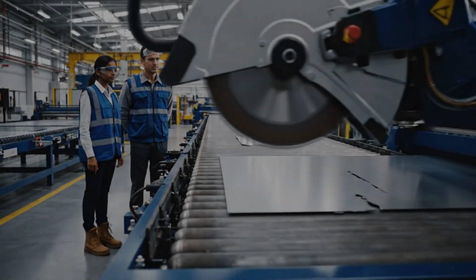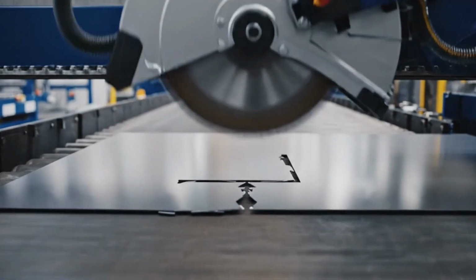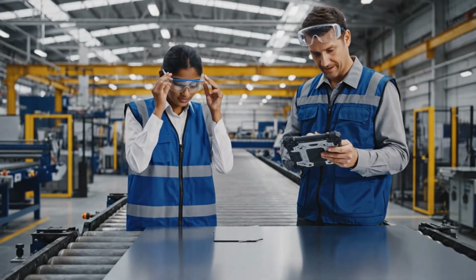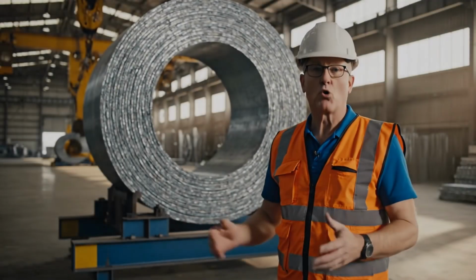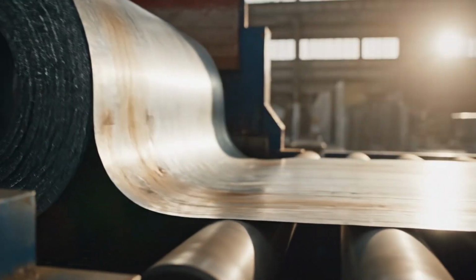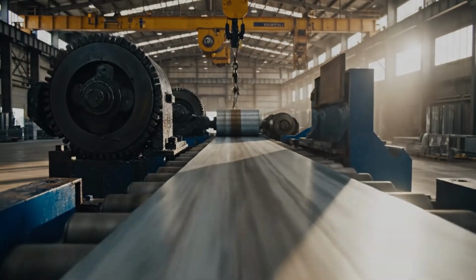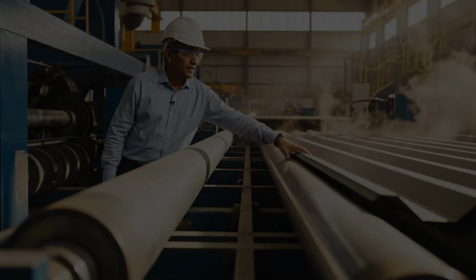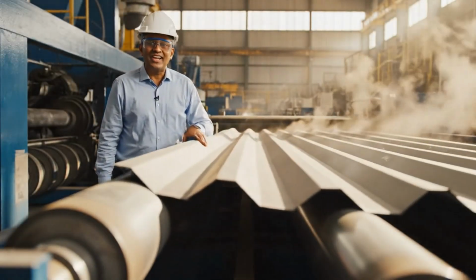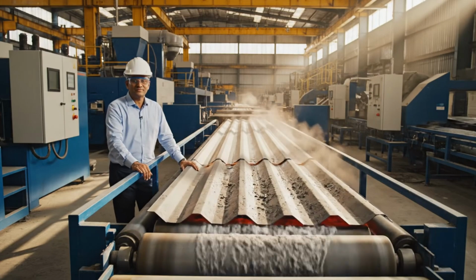This is where flat steel is transformed into the familiar corrugated sheet metal. The rolling mill, with its 15 to 20 rollers, continuously bends the steel to the required shape, height, and stiffness. The corrugated shape not only improves drainage, but also increases stiffness and dissipates heat more effectively. The steel is rolled at a speed of 40 to 60 meters per minute, producing beautiful, uniform, and millimeter-precise sheets. But the journey doesn't end there.